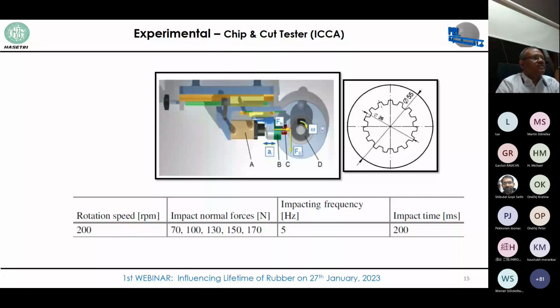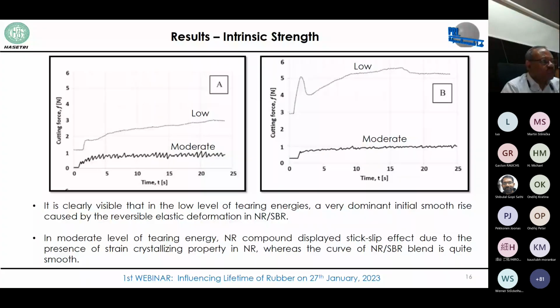Coming to the results for the intrinsic strength, these are A and B. A is for the natural rubber compound and B is for the natural rubber SBR blend compound. These plots are cutting force versus time. You can see that at low tearing energy level, in the case of NR-SBR, there is a sharp peak initially, and then it is smooth in nature. Another observation is that there is a lot of fluctuation in the natural rubber based compound, which we can call the stick-slip effect. That is due to the strain induced crystallization effect in natural rubber, which is not that prominent in the NR-SBR blend.